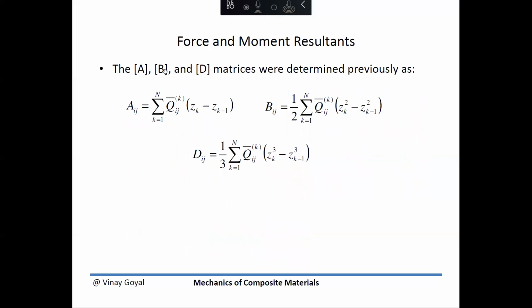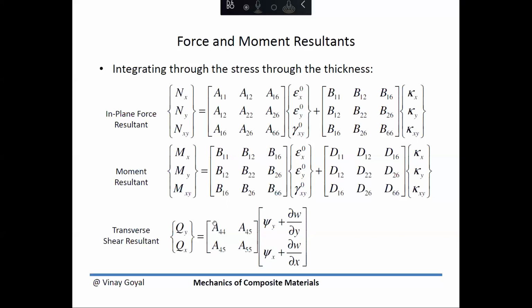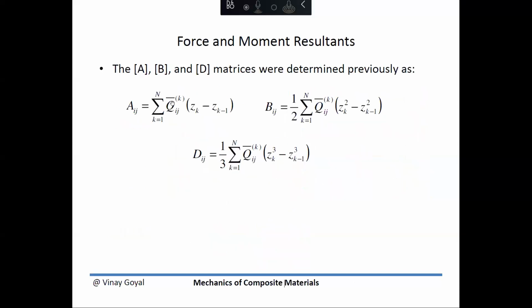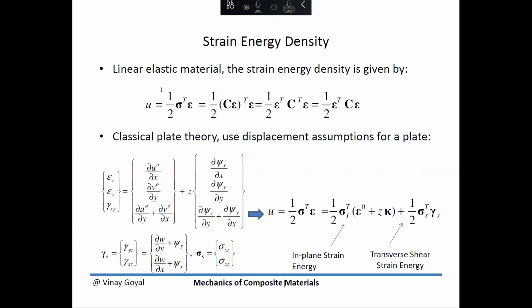If you recall, the ABD matrices were calculated in this manner, and in today's edition of calculating A44 and A45 and A55, you will simply be using this equation right here, where Q bar bar was fully defined earlier, and it can be calculated for every ply, and it's going to depend on theta. This term right here depends on the location through the thickness of that particular lamina, but you'll be summing it all up from the bottom ply to the very top ply. Similar calculations we discussed before.